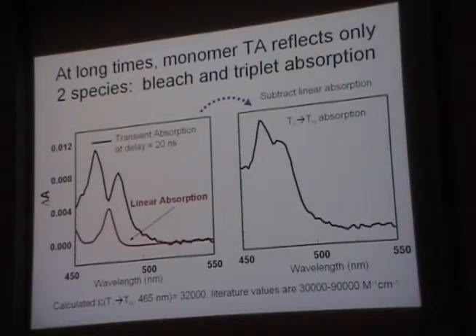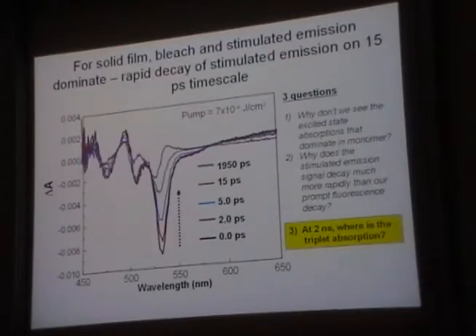So what do we expect for the solid? Well, if it's exciton fission, we know what we expect, right? That singlet is going to appear, and then within, say, 100 picoseconds or so, that's the nominal exciton fission time, it's all going to go away, and we're going to be left with one huge whopping triplet absorption. Okay, and that triplet absorption is probably going to be about 465 or maybe a little bit different. That's what we expect to see if we're right about exciton fission. Okay, that's what Stefan Lochbrunner expected to see.